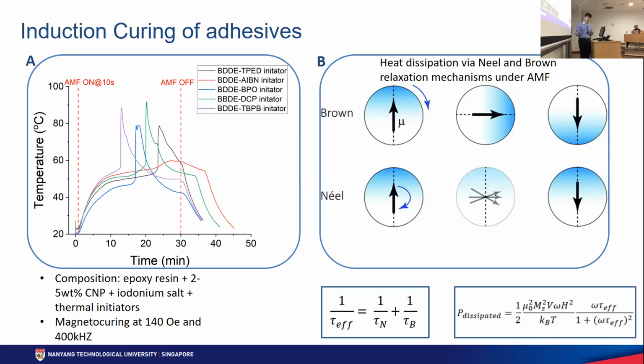So let's look at the graph on the right. This is a typical magneto-curing temperature profile. So as you can see, after around 10 minutes or so, we see a spike in temperature, which signals the simultaneous exothermic reactions that are happening, and curing is happening. But I want to point out something interesting. That is the red profile. So here we don't see a defined peak in the temperature, which means that we're having these exothermic and endothermic processes during curing balancing each other out.